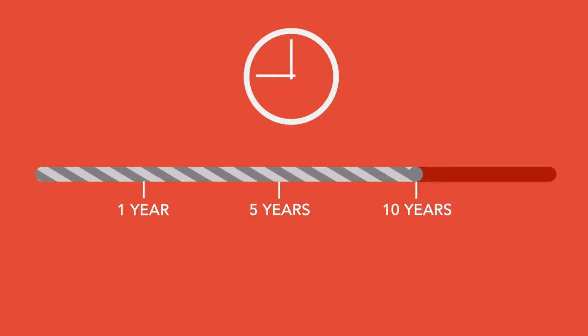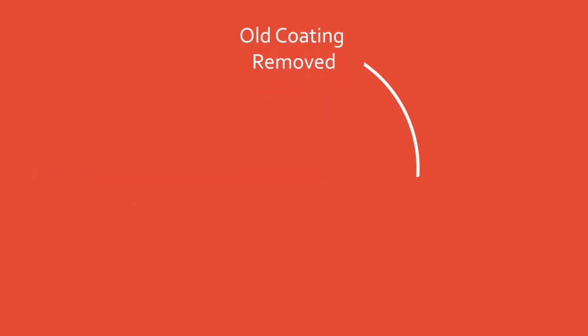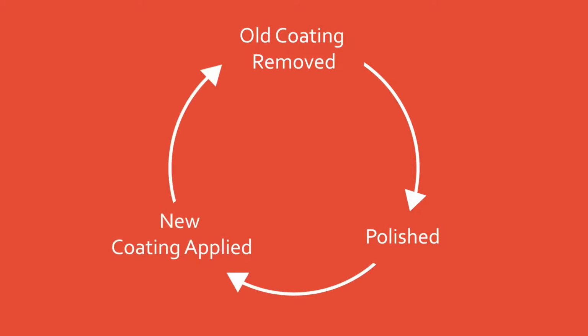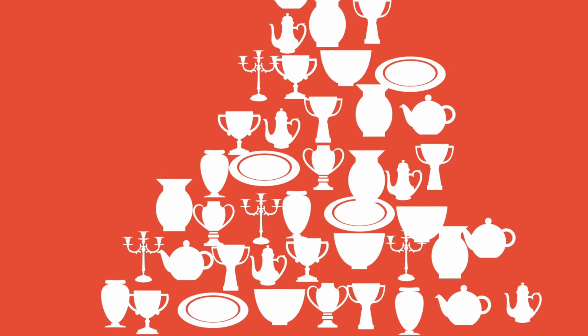The best way to protect your silver is to apply a coating, and currently museums use a plastic coating that lasts about 10 years. At that 10-year mark, the coating has to be removed, the silver polished, and a new coating applied. For museums with thousands of silver objects, this creates a nearly constant cycle of damage and recoating. My research is looking to break that cycle by creating a new coating enabled by nanotechnology.